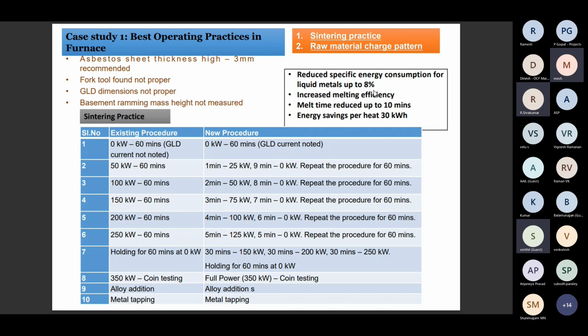Similarly, the power capacity is gradually increased compared to the existing practice, from 25 to 50 kilowatt, then 50 to 75, 75 to 100, and 100 to 125 kilowatt, and the timing is also increased from 1 minute to 2 minutes, 3 minutes, 4 minutes, 5 minutes. This is the practice we followed, and finally holding for 60 minutes at 0 kilowatt, and finally the metal was tapped. So, next one.